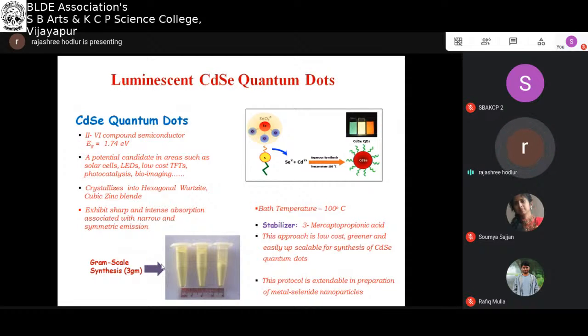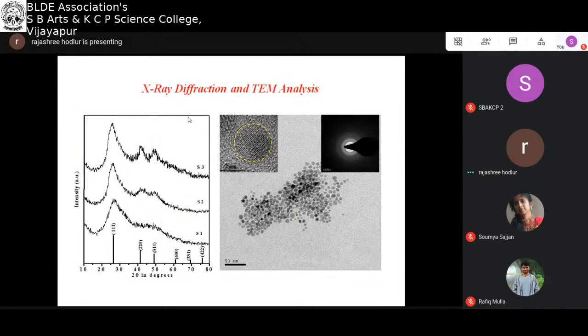So this figure shows the one batch synthesis. It was nearly in 250 ml, we could obtain nearly 3 grams. So large scale synthesis was possible using the aqueous liquid phase synthetic approach. We carried out various characterization to confirm their crystallinity using X-ray powder diffraction, and TEM analysis mainly was carried out to confirm its crystallinity.